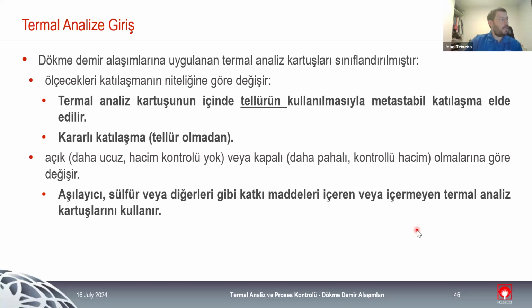and with replicability in time. And for this type of analysis in the base metal, we use cups with tellurium. And the tellurium is there to consume all the carbon and to transform the carbon into carbides, so to speed up the solidification process. So we don't have anything happening in the eutectic, so we have a straight line, and it's easy for the system to identify all the different spots that they need to identify. During production, after magnesium treatment, after inoculation, we want to see the changes in the melt with these production steps. So we use cups without anything.